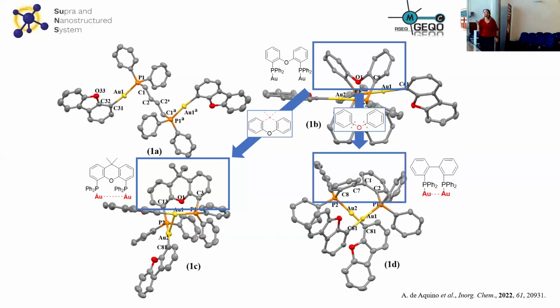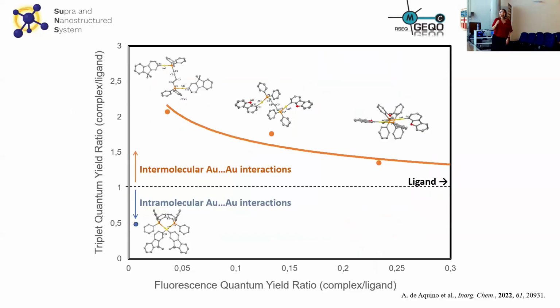And we could observe that, in fact, these interactions are stable in solution. Okay, the differences in the luminescent properties are not so straightforward like in the solid state. In the solid state, we can have a direct correlation between the distance between the metal centers, independently if it happens in an inter or intramolecular way. Here, it is not the same if we have intermolecular contacts or intramolecular contacts.